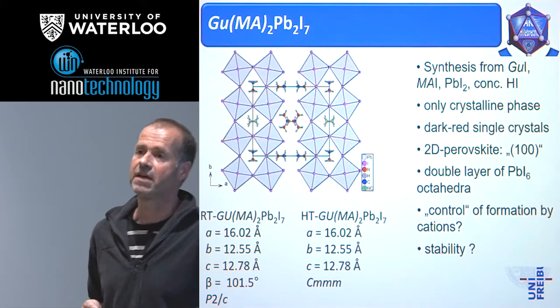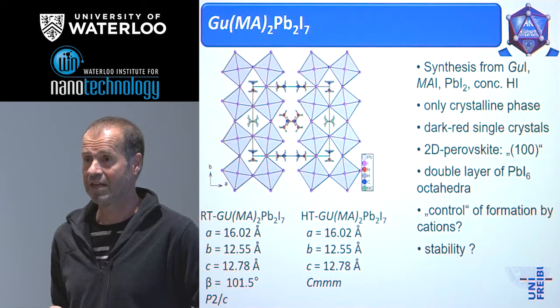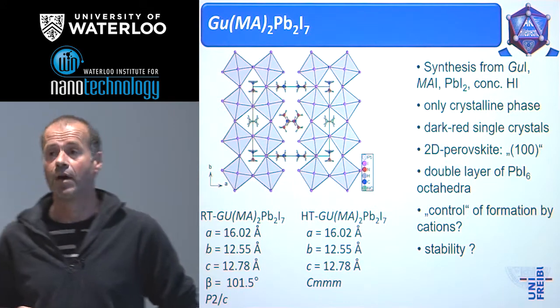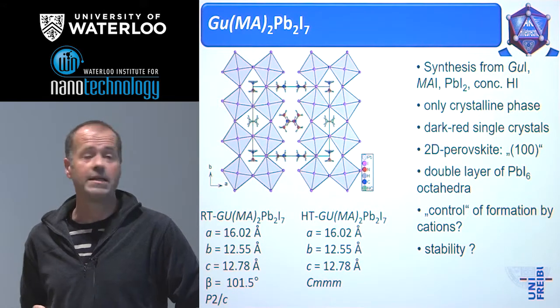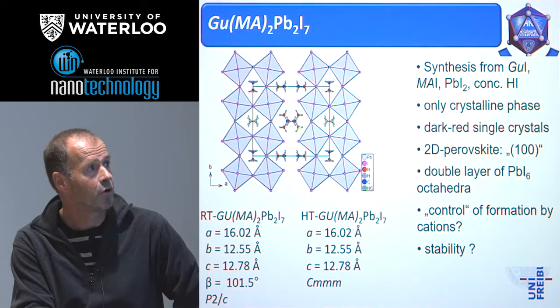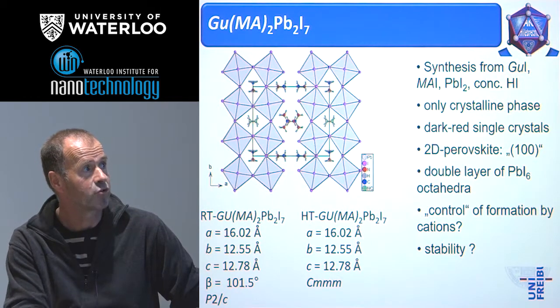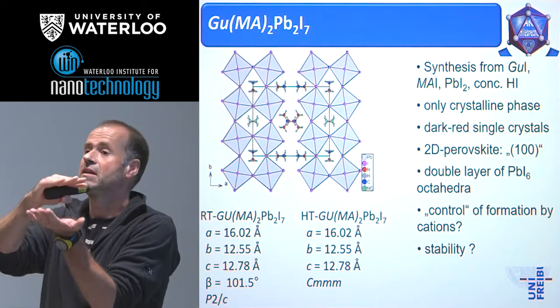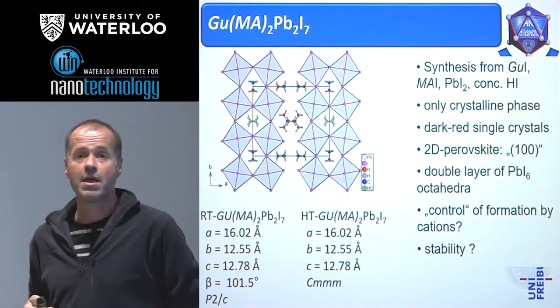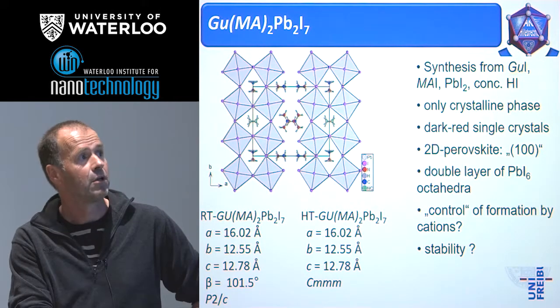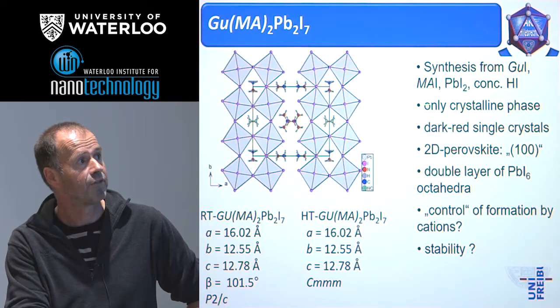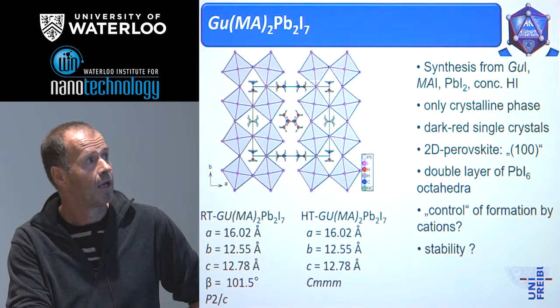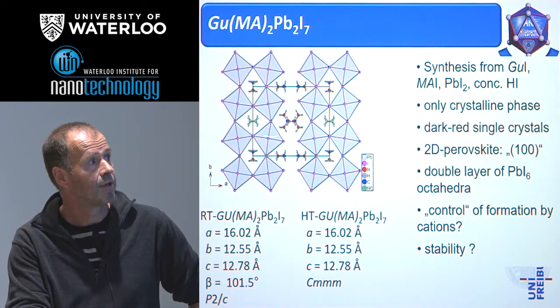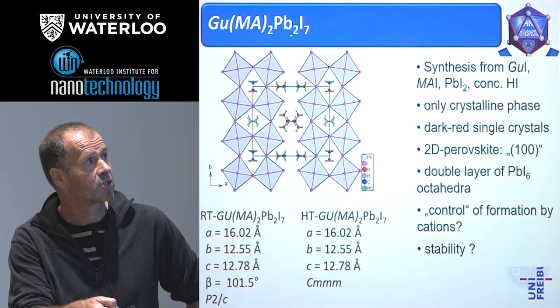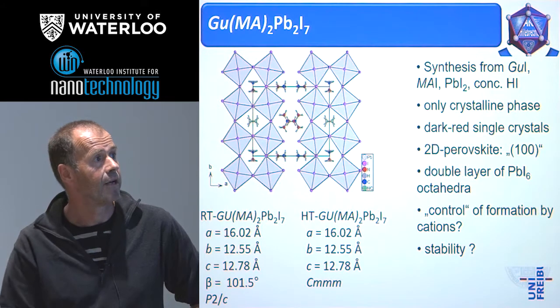This organic cation is significantly larger than the methylammonium, and it has a significant interaction according to the formation of hydrogen bonds, and it's more or less a disk. It's not a sphere. We could synthesize it under the usual conditions, and we found that the only crystalline compound is a layer structure with 3 cations, 2 lead, and 7 anions.